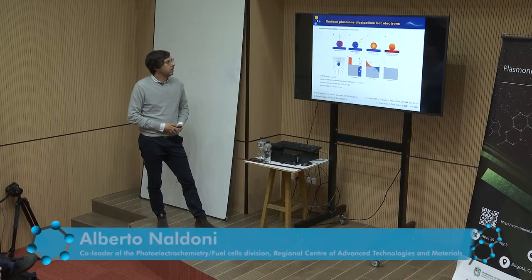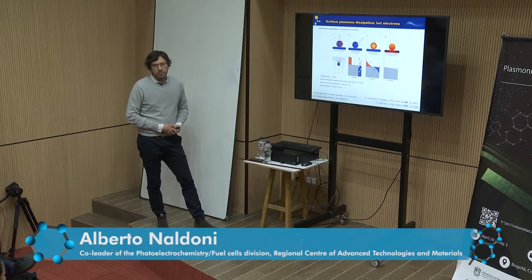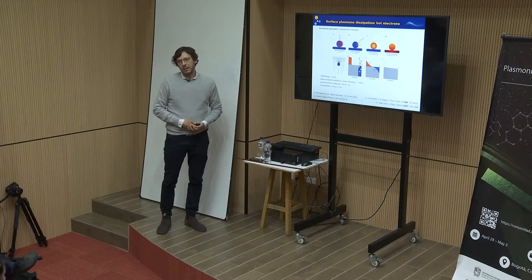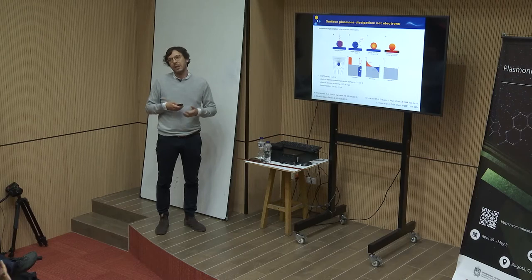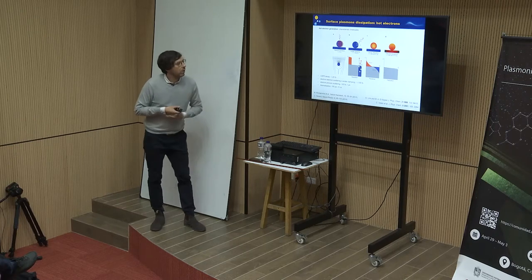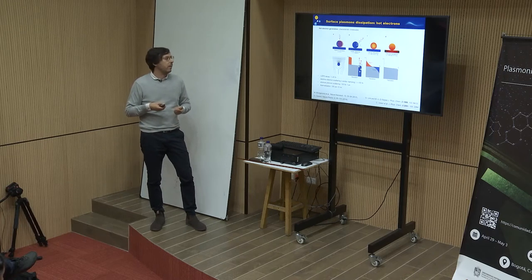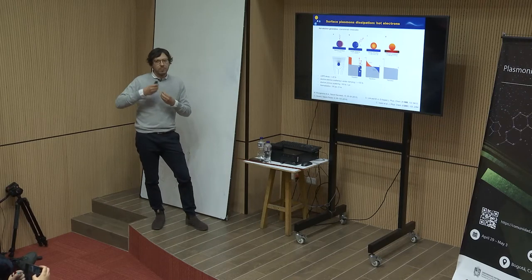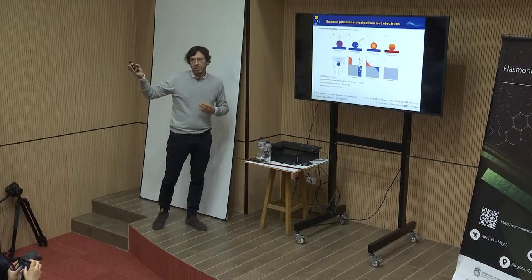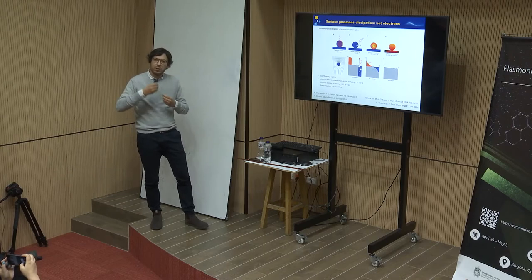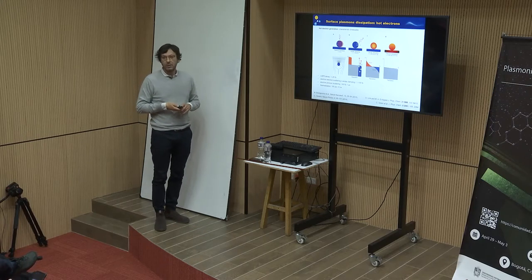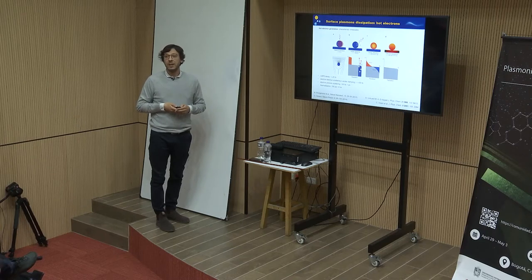Is this hot electron generation only one way of dissipation, one of the possible decay modes? No, actually, as far as I know, there are two ways. So this is one way. The other way is when we have a semiconductor or molecules in contact with the metal, and it is called interface damping. Basically, the electrons of the plasmon, as we'll talk about later, decay directly into the unoccupied orbitals of the molecules or the semiconductor. So there is an instantaneous generation of charge separation states at the interface, and there have been demonstrations of this. You also have radiation, radiation of electromagnetic waves. Yes.